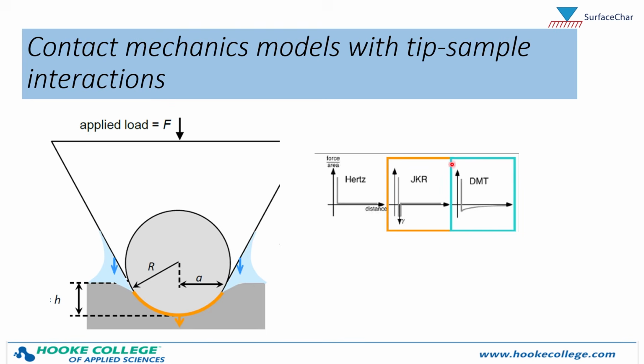The DMT model in turquoise here accounts for adhesion in this area right outside the contact area. And if we look at the force versus distance plot for what a DMT model looks like, it's shown here. So this part here is the adhesion portion that is modeled right here. That's in contrast to the Hertz model. When we look at the force versus distance on the Hertz model, we see there's no adhesion. The JKR model models adhesion right in the contact area, right between the tip and sample, and its force versus distance plot looks more like this, where the JKR can model more significant adhesion than a DMT model. So the DMT model is a weaker adhesion than the strong adhesion we can see with the JKR.